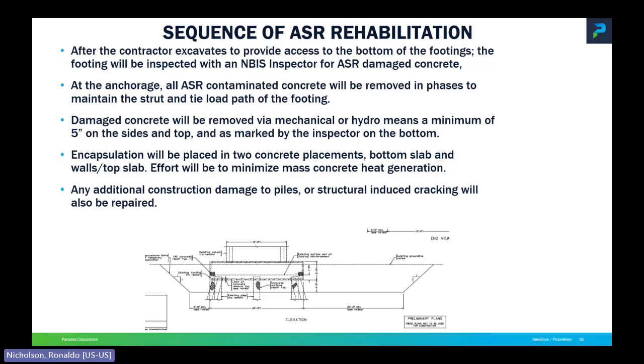Our goal was to do the encapsulation in 2 placements, the bottom slab and then the walls and top slabs. So there was also a mass concrete concern and heat generation due to that on both the existing concrete substrate as well as the placement. Again, this was fiber reinforced concrete that we're replacing. So there were a number of, I'll call it, challenges of developing this mix design for the concrete, because while you wanted it to be impermeable, you also needed the flowability, a self-consolidating effort of the concrete in order to make sure that it covered all these substrate areas up to 2 feet for the encapsulation.